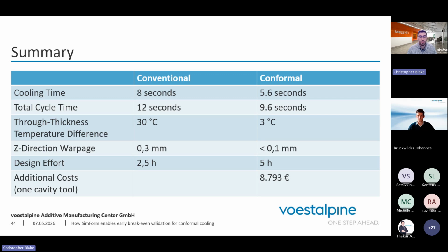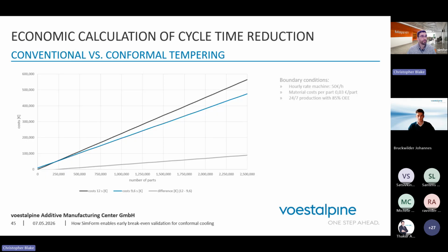There is a difference in design effort, obviously, as reported by my colleagues at voestalpine. It was about 2.5 hours to get the conventional design and up to 5 hours to get that conformal cooling design. There's also the additional cost of printing that cavity tool of about 9,000 euros. But despite this, as Johannes will summarize in the next slide, we do get a very interesting economic savings because of the reduction in cooling time.